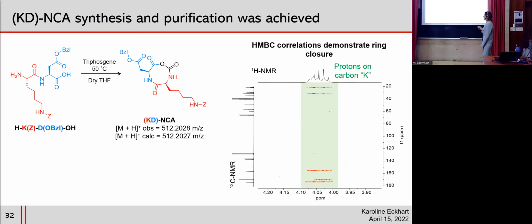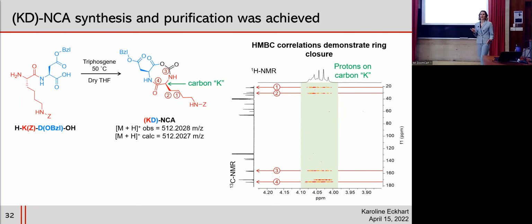And with the HMBC, this is pretty cool. We're zoomed in on the protons on carbon K in the proton NMR. So we're looking at this proton, and HMBC is showing us correlations to carbons that are 2 to 3 bonds away. We can see here that the proton on carbon K is correlated to 4 carbons, which can be identified as these 4 carbons here. So this data is confirming ring closure, because in the starting material, the proton on carbon K is only correlated to 3 carbons. But when we close that ring by this anhydride, we get an extra correlation.